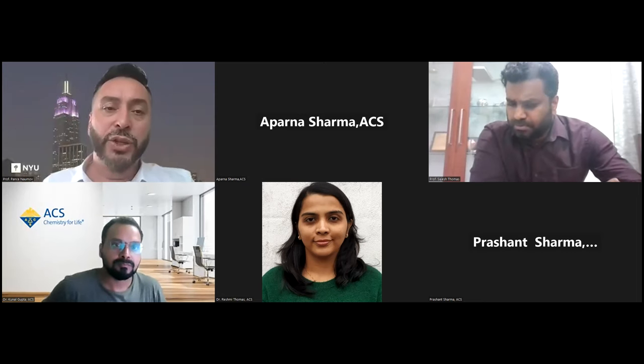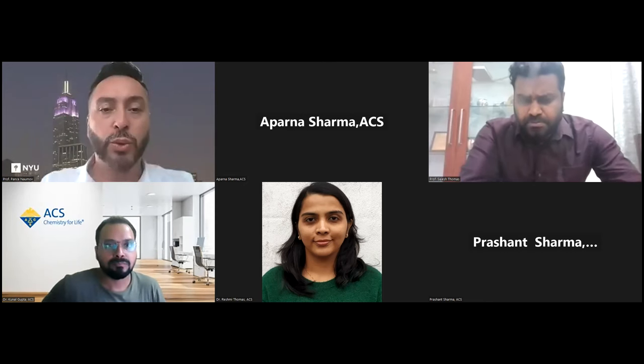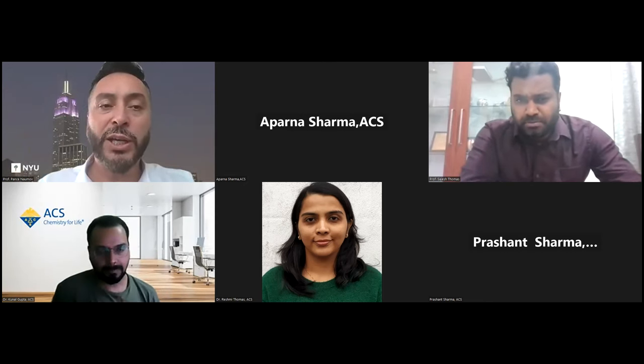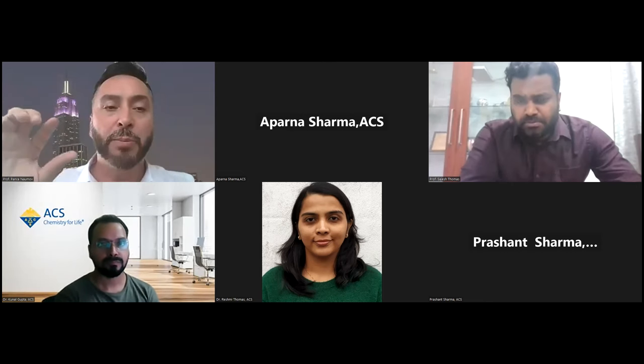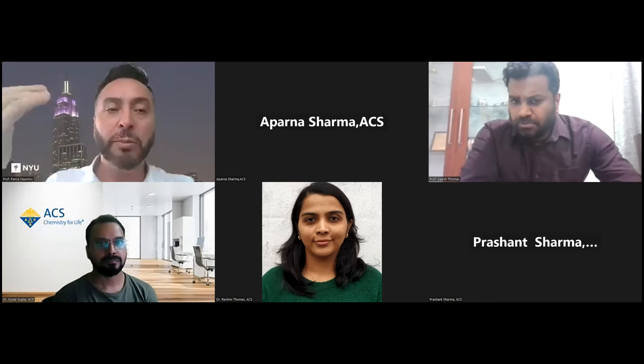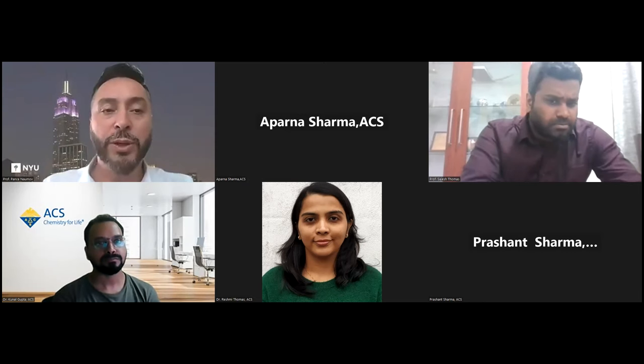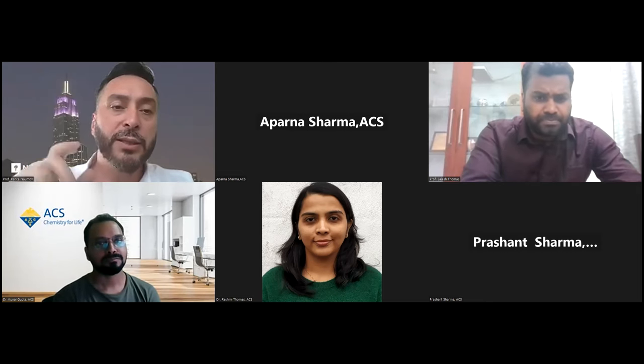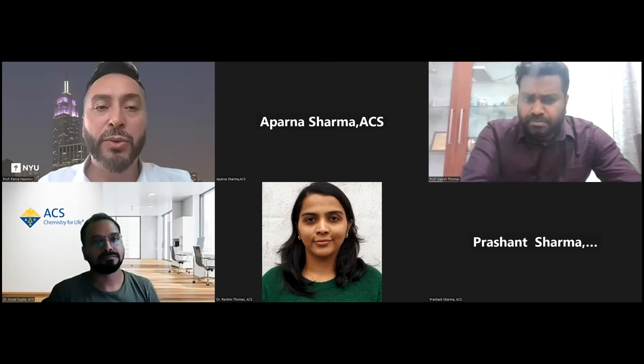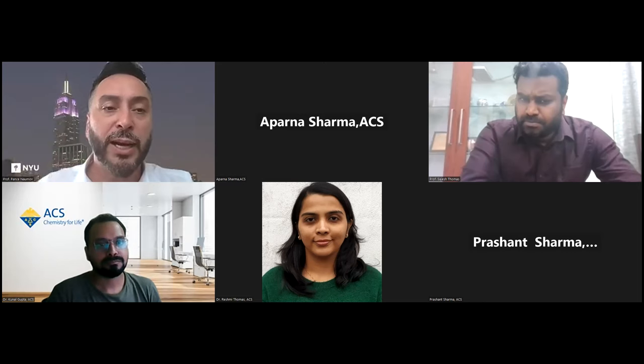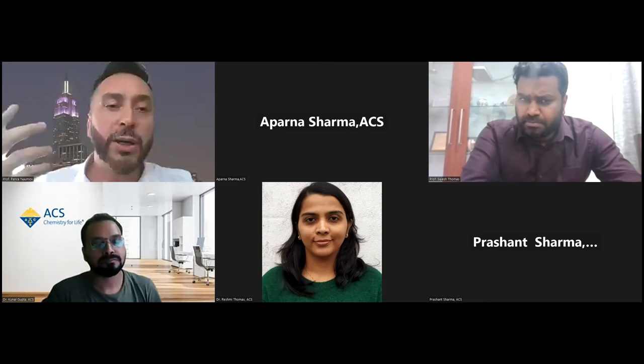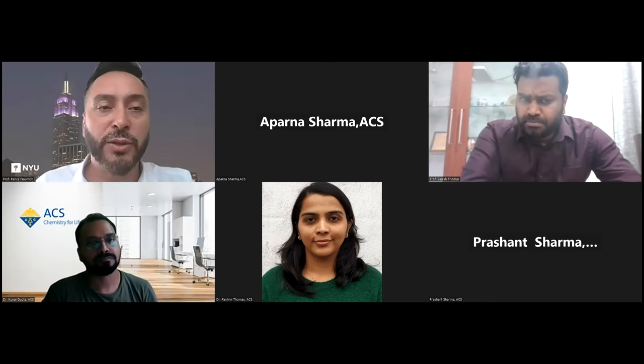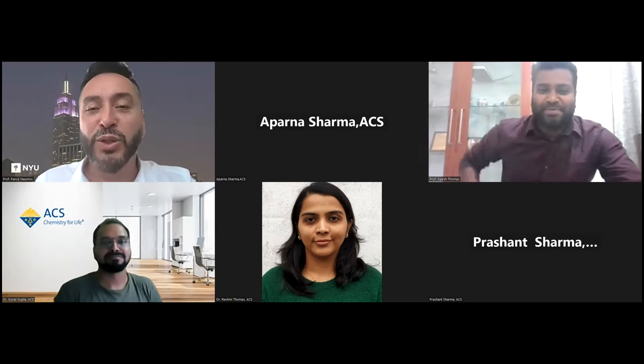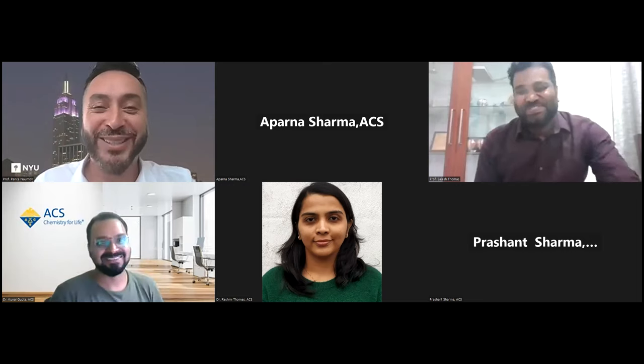The mechanical pressure is used only in one way of the process to induce the formation of the second phase and to contribute to the formation of the bilayer. But the temperature is used as a second stimulus to push it back. And so we have two stimuli, and this is why we can switch between the two different states by using this crystal. But of course, the material memorizes that change, and of course, it goes back when we go to the other state. So this is possible due to the memorization or history of the sample that remains in the crystal structure. Okay. This would be the most qualitative explanation, but of course we can discuss more details offline.